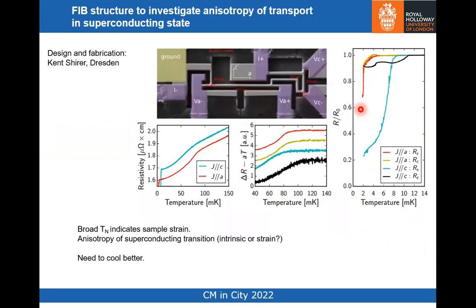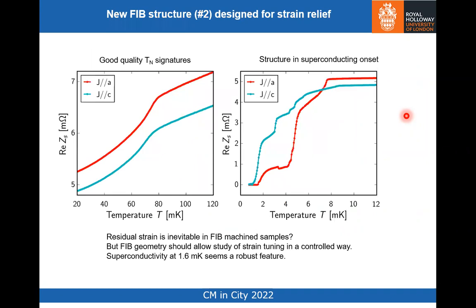Because of this, if you remember, various signatures in the contact resistance and the sample resistance, where we believe that the contact resistance will be more sensitive to the resistivity along the C-axis. We were concerned to try and look at anisotropy of superconducting onset, but it's very difficult to disentangle that from the sample strain that exists also in these FIB structures. That's the take-home message from that.